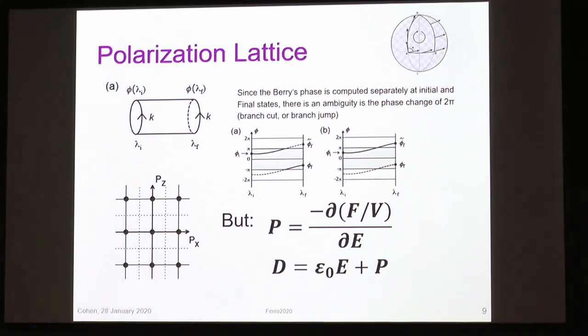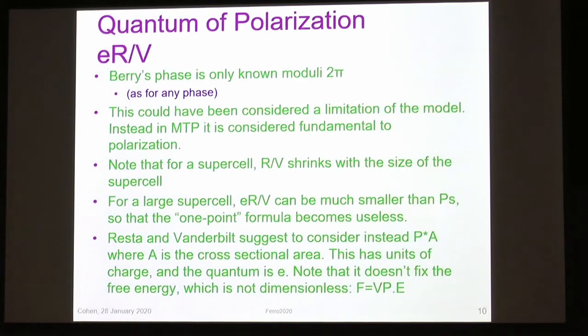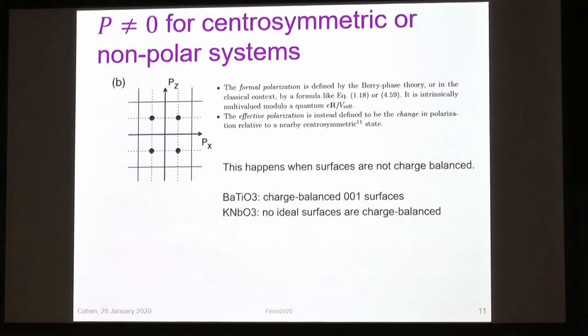But the problem is really when you pick one point and just want to get the polarization at that point without considering a path. So this is the issue with the polarization not being zero even for a centrosymmetric system. The argument is that the polarization lattice can be symmetric about zero, and then it still meets the symmetry of being centrosymmetric. So you have a bunch of lattice points of possible polarizations, symmetrically around zero, but zero is not one of the points on the lattice.